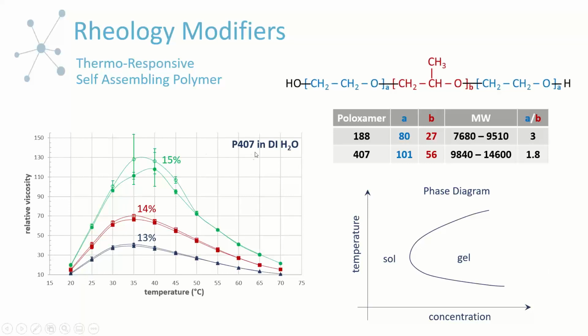And so what we have here are one of the particular poloxamers, the P407, which is the one that kind of peaks in viscosity close to body temperature or skin temperature. And we can see, in addition to the temperature sensitivity of the relative viscosity, we can also see the sensitivity of the concentration of this particular poloxamer. And so this is just a more complicated type of rheology modifier if you want to introduce temperature sensitivity and see a transition from potentially something that is a low to moderate viscosity fluid to something that is a viscoelastic solid or a gel.